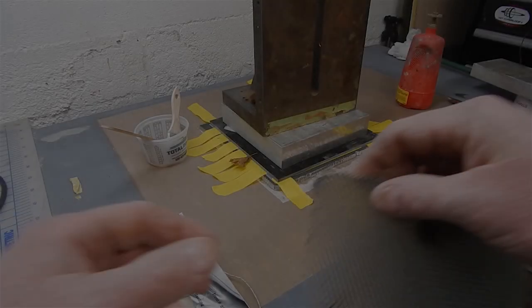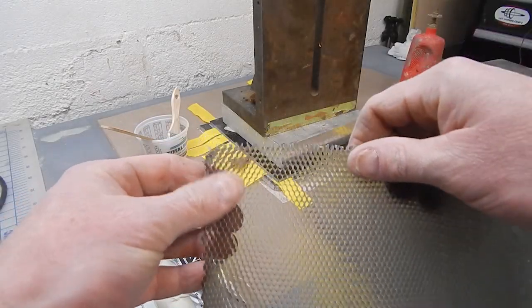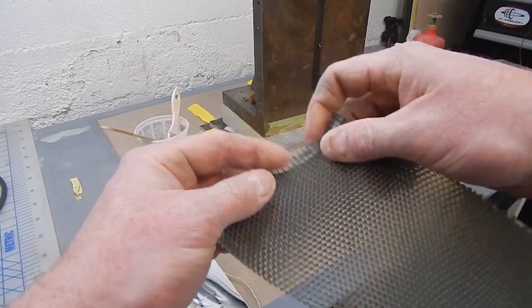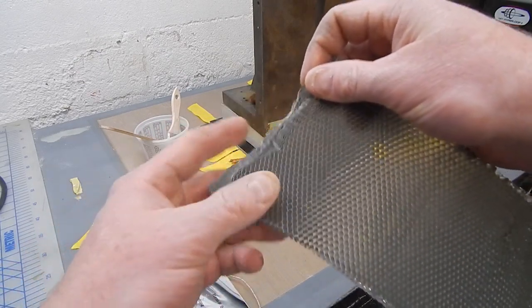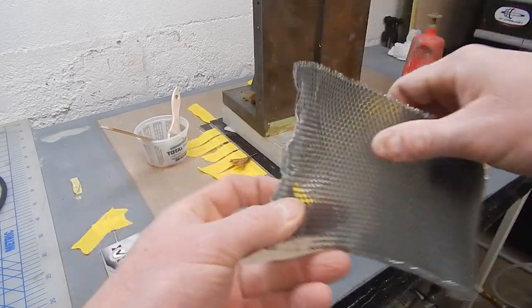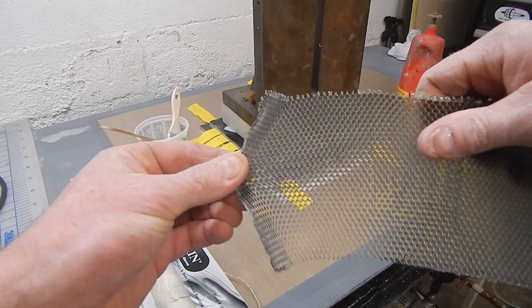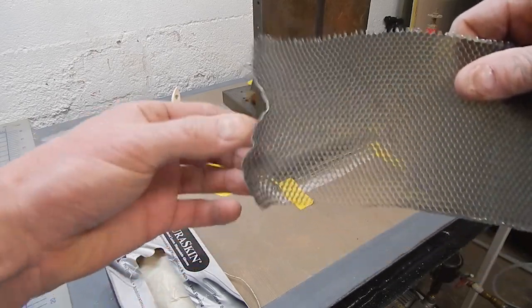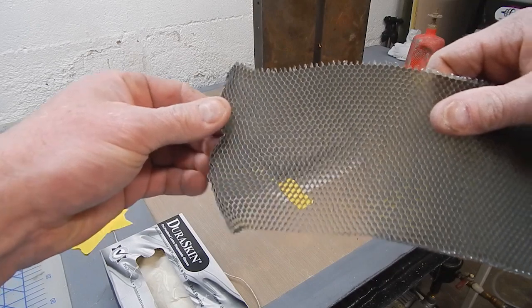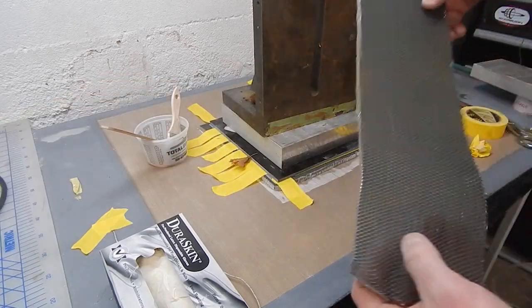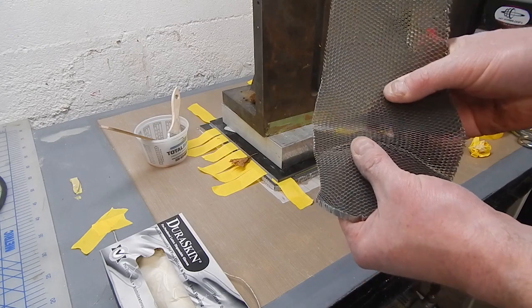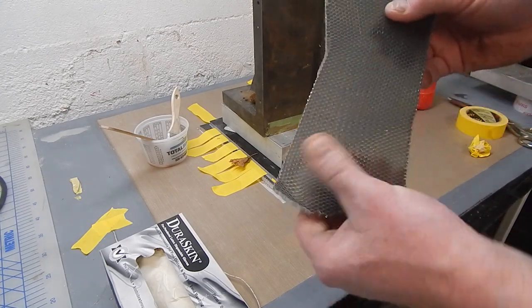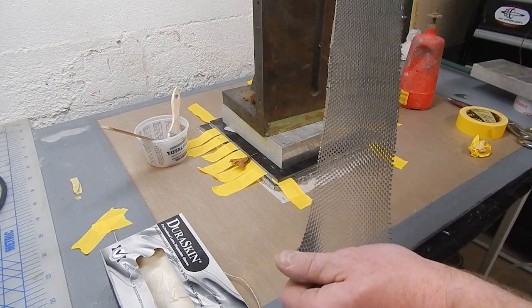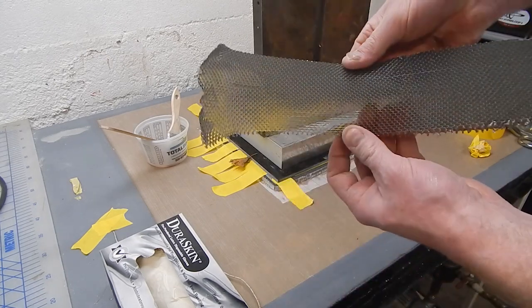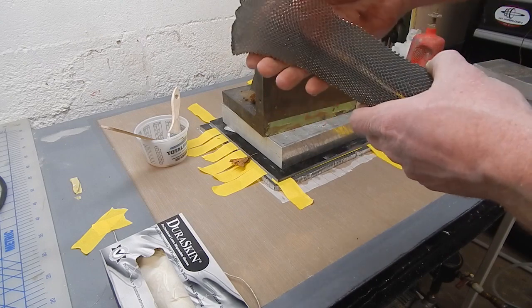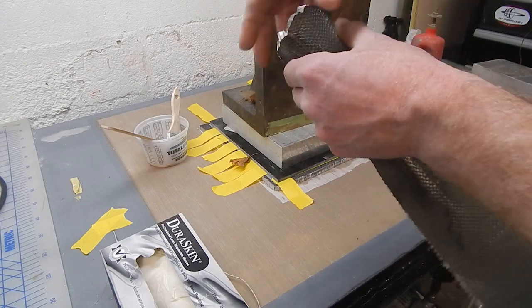So, let it all cure, and here's a quick look at the aluminum honeycomb. This is nice stuff. You can see it's made in this compressed form and then expanded by pulling it open, and that gives the cells their shape. It can be got with different geometries, different cell shapes, and different levels of expansion. By pulling it, stretching it the long way, the cells are what's called overexpanded, where the cells become almost rectangular, and that allows you to form the honeycomb into different shapes, different curves.